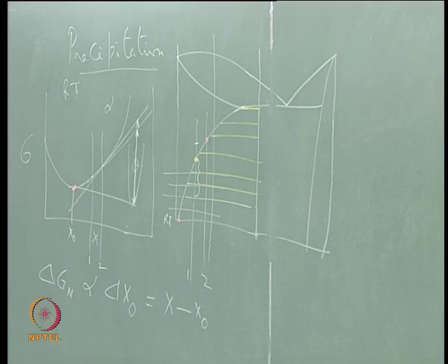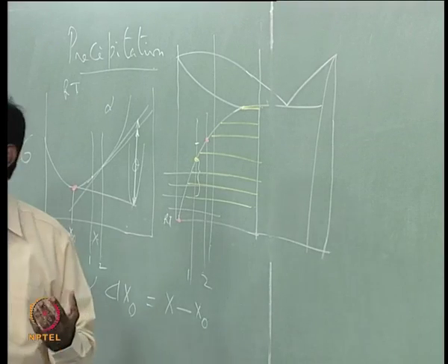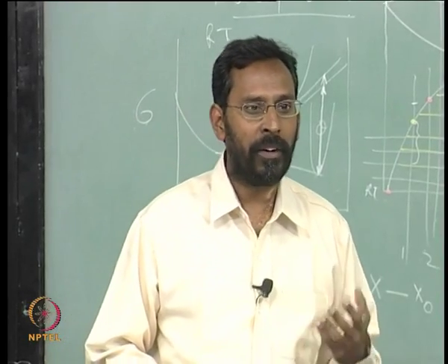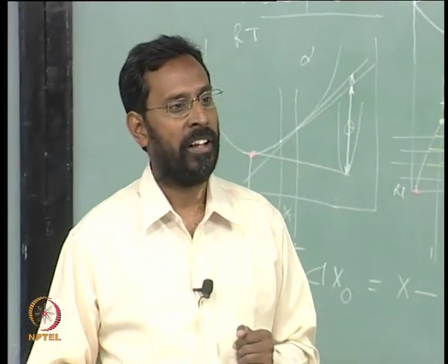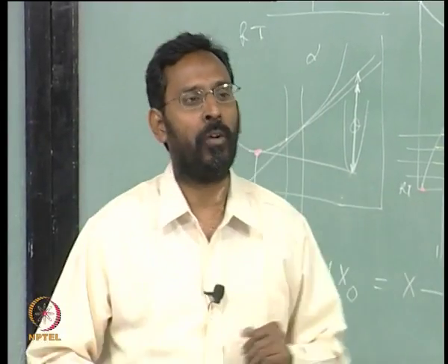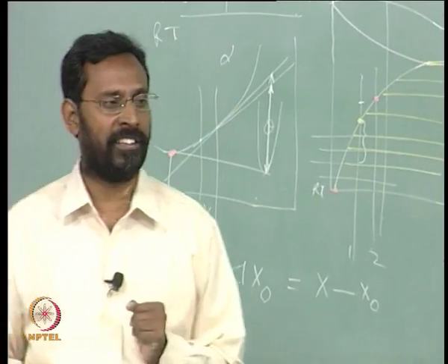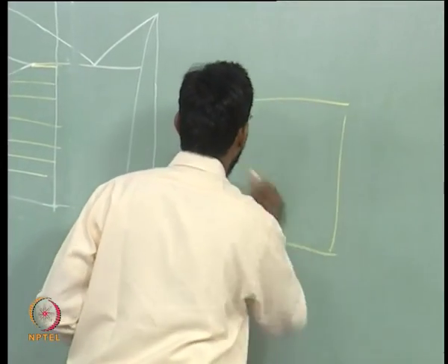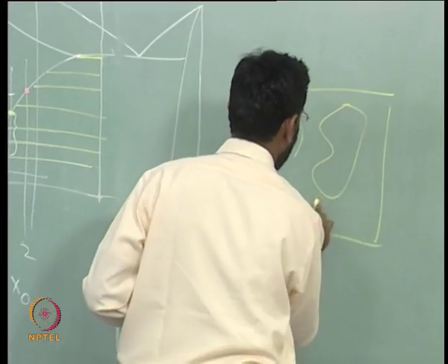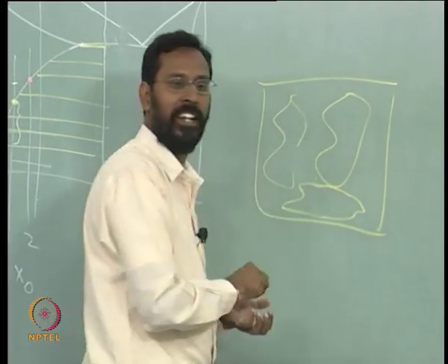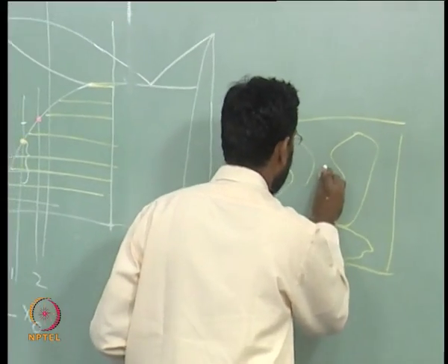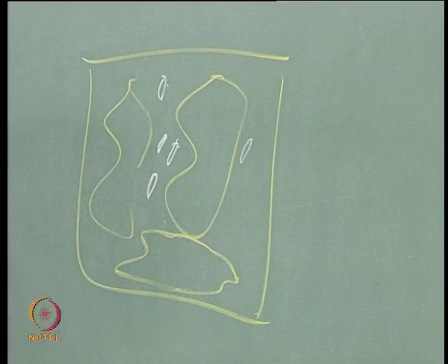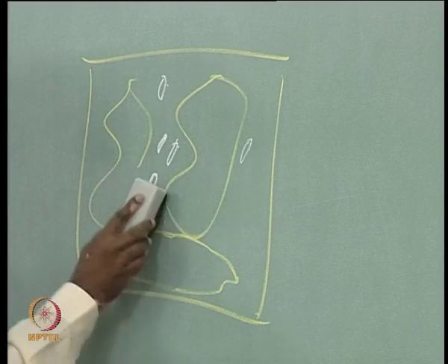It cannot nucleate inside. So, in principle it would possibly nucleate on the existing theta which is there from solidification, because theta is already there in the eutectic mixture, so the new theta gets precipitated over that because it does not need further nucleating sites. So, you will usually see the microstructure would look like the dendrites, and in the interdendritic regions you will have, whatever may be the morphology. In this particular case you actually see a lamellar morphology. So, you will see lamellae of